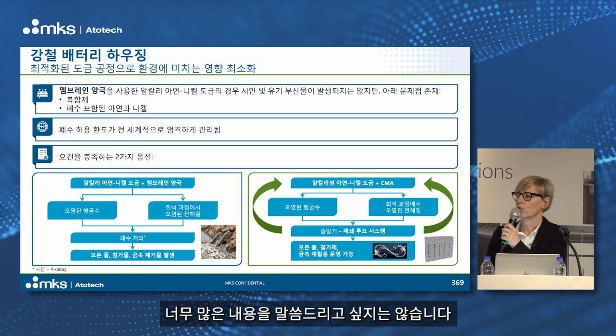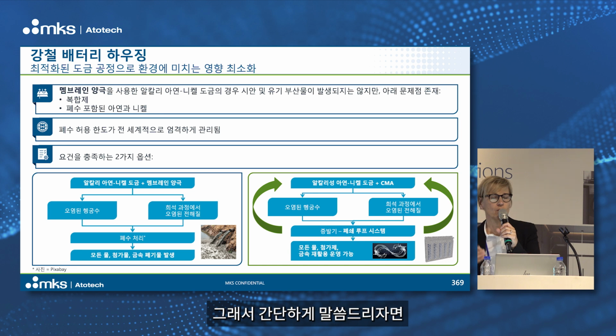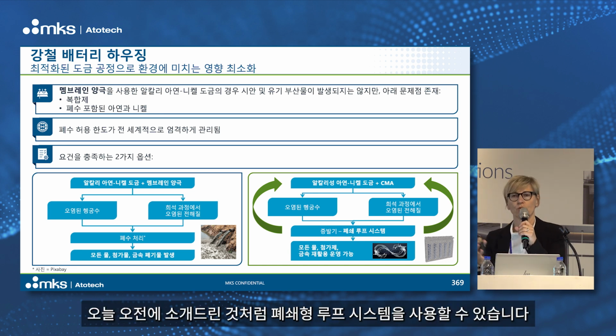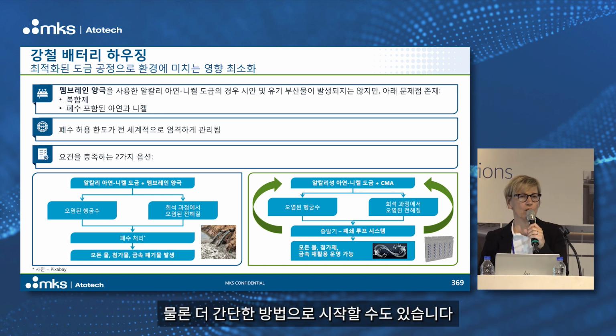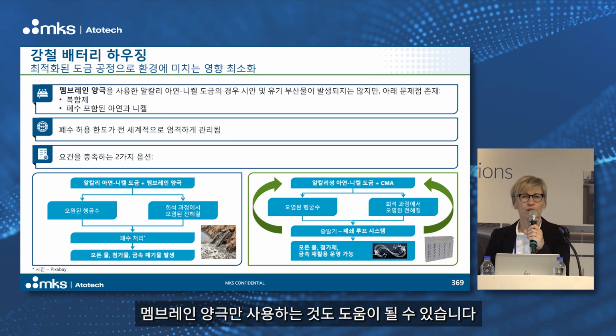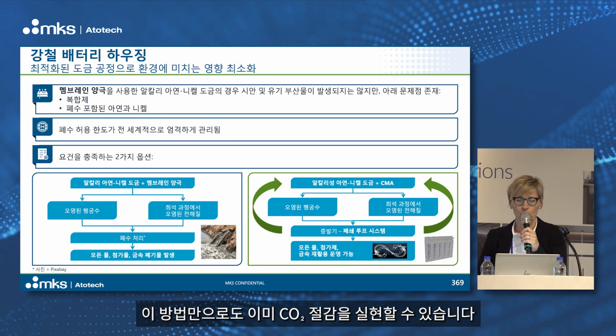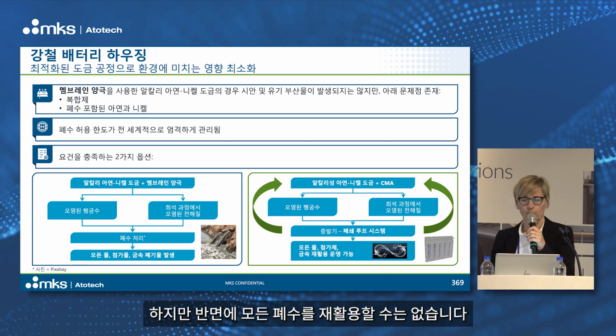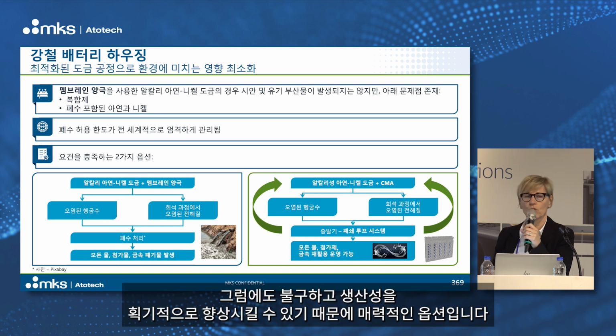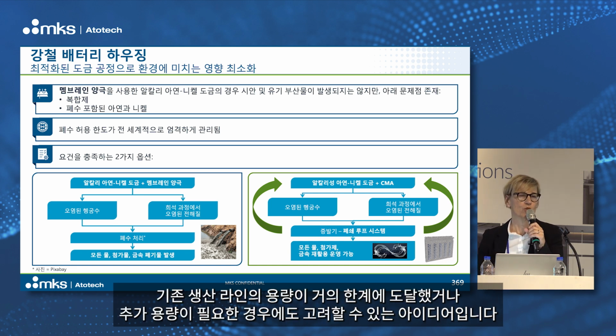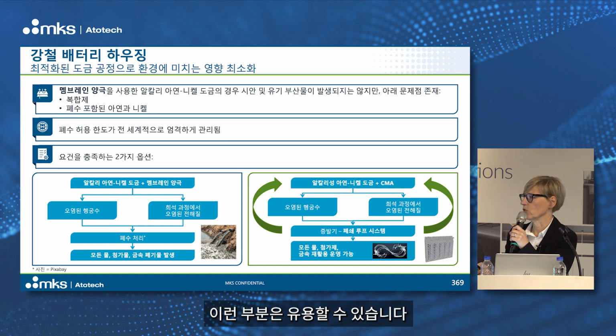I don't want to bother you too much, therefore only very shortly. You can do that with this closed loop, like I introduced to you this morning. Of course, you can also start in the easier way, only using the membrane anodes already. That will also help you save CO2. But on the other side, you are not able then to recover all the wastewater. But it's also attractive because it helps to increase productivity dramatically. So that can also help if there is a line which is already close to the end of capacity and you need further capacity, then this can also be an idea.